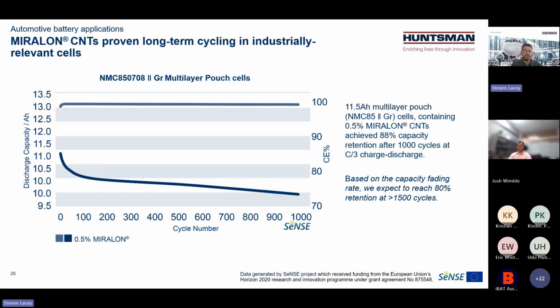So if you would extrapolate this out and see the capacity fade continue, we would expect 80% limit around more than 1,500 cycles. So in this case, this was a very industry relevant cell, also for automotive, which was also the target for SENSE project.